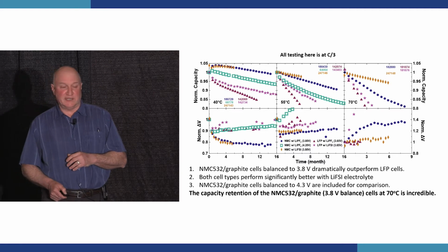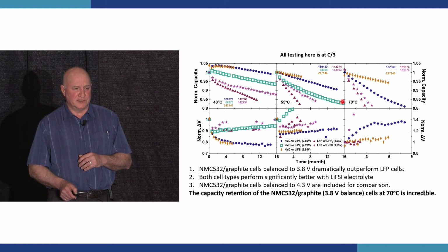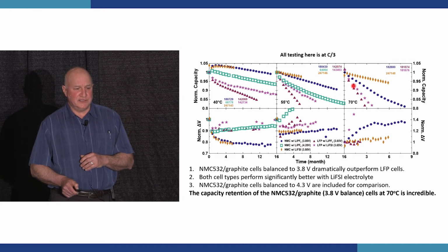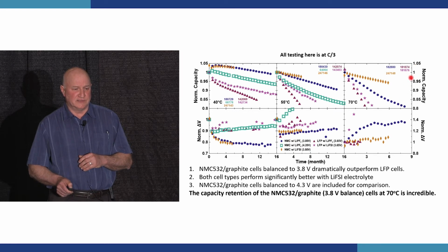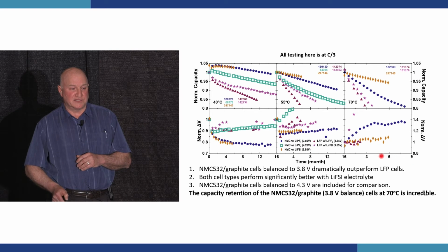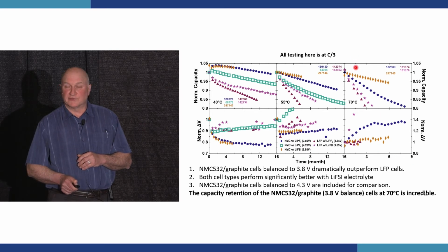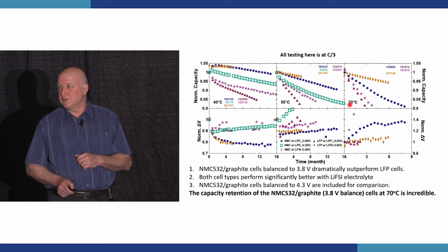Okay, so this is a very busy slide. I really just want to concentrate here on the upper right panel that you see here, okay? So these triangles that you see represent the normalized capacity in the cell versus the testing time in months, where all the testing is done at 3-hour charge and 3-hour discharge. So the triangles are for lithium iron phosphate cells with LiPF6 electrolyte salt. And I showed you before that when you changed to LiFSI, things became better, and they do. This testing is at 70 degrees centigrade, by the way. It's hugely, way beyond where you would ever think about testing lithium ion cells.